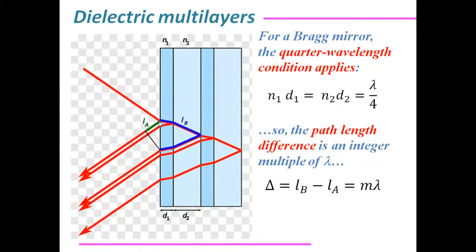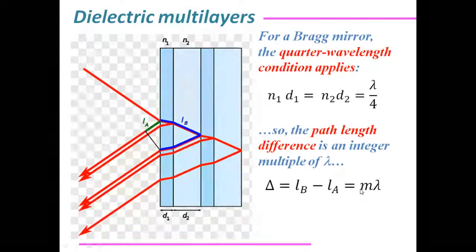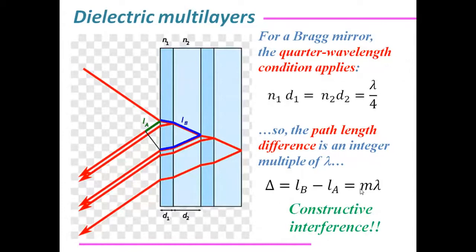It's essentially optics 2 that the path difference between the first beam, LA and LB, goes through, reflected, partially transmitted, partially reflected. So, as you can see, it's an interference pattern. And you know when this path difference is an integral multiple of lambda, we get constructive interference. So this is the highest possible reflectance we achieve under this condition for the Bragg mirrors.